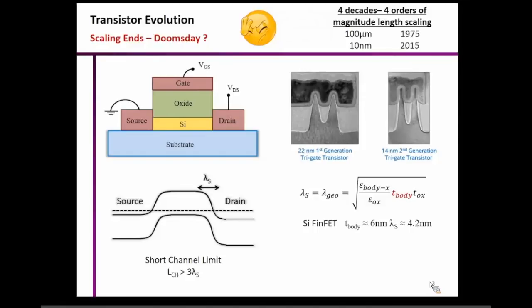The problem is, if you try to scale the thickness of the silicon film below 6 nanometers, you run into the quantum regime where silicon no longer remains a semiconductor because its band gap starts to increase. So that's the problem we have in hand, which is a material limitation. And this is where we need innovation in materials.